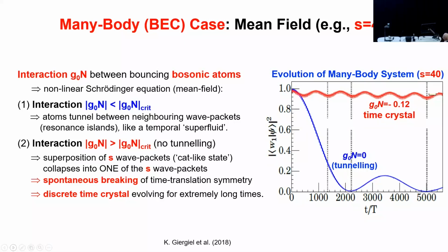Or, if you have a larger interaction between the wave packets, this stops the tunneling and you get a superposition of S wave packets, which is like a Schrödinger cat state, which collapses into just one of the S wave packets. Any very small perturbation, of course, does this. And so you get spontaneous breaking of time translation symmetry. You get this discrete time crystal, which in principle can evolve for extremely long times.